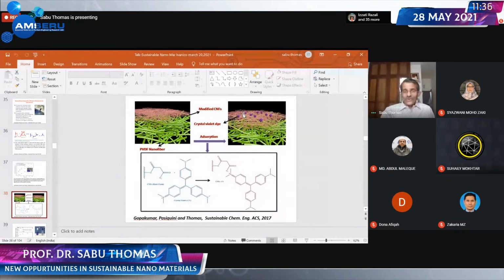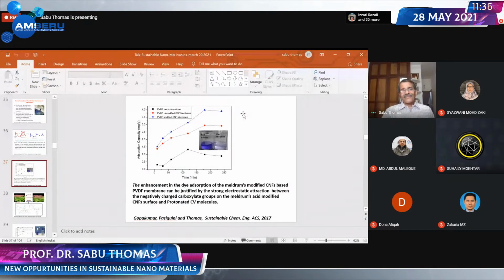Now I want to show you what is the filtration efficiency. Look at the filtration efficiency. This is the commercial filter, a bi-layer filter, where you can see the removal of crystal violet. Not very efficient. But if you modify the top surface of the filter with nanocellulose dispersion, look at this. The red one is neat nanocellulose. On top of this, the best one, the chemically modified nanocellulose with COO minus group. Look at this. The efficiency became 4 milligram per gram. Unmodified, the efficiency is something like 1.5, 1.25.